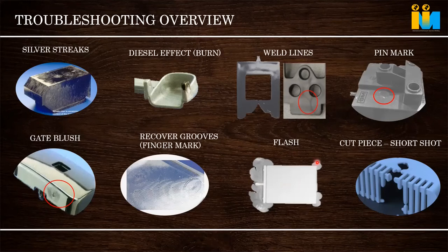And one more thing: wearing out of the parting line could be due to multiple reasons. Suppose the cavity and core are butting, and there is a tonnage we are applying. Our steel butting area should be sufficient to take care of the clamping force of the machine. For hardened steel, it could be like 20 kilogram per mm². If that sufficient area is not there, the cavity and core butting area will get compressed and damaged, and flash can also come at a later stage.